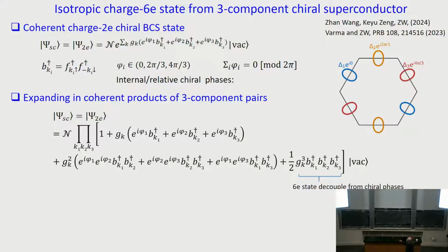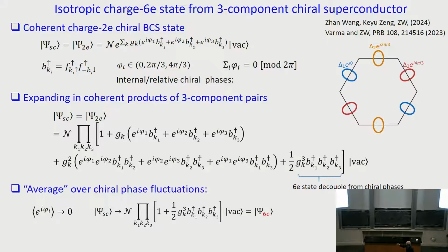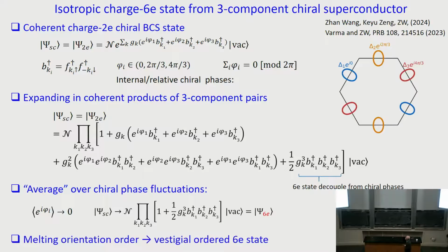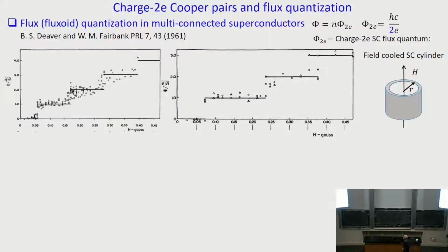So the 6e state decouples from the chiral state. Right? The BCS wave function contains all pairs, 2e, 4e, 6e, and everything. But if you write it in the coherent state, it's that of the 2e. But now things can change if the chiral phases fluctuate strongly. So let's see, this average, this fluctuation kills all of these. Now the only thing surviving is this. This is a phase coherent state of 6e. So that's really what I mean by there is a chance, by melting the 2e, I can get to the 6e. Right? How do we see the 6e?